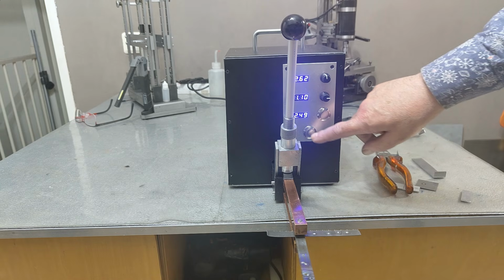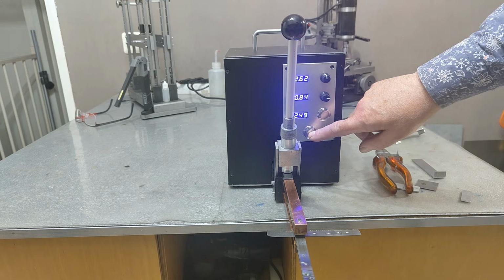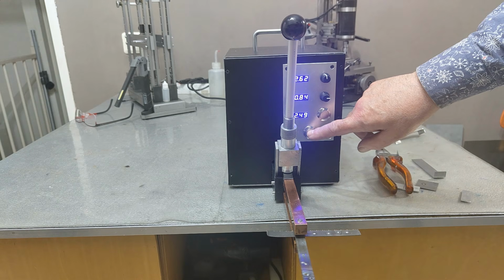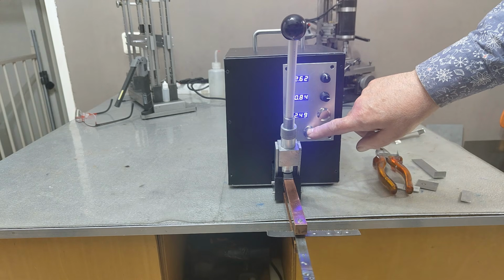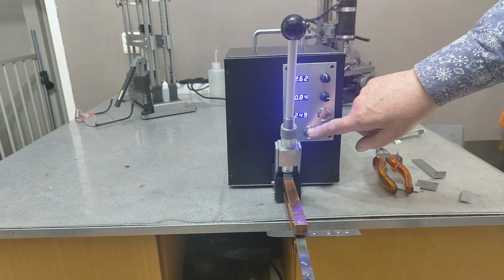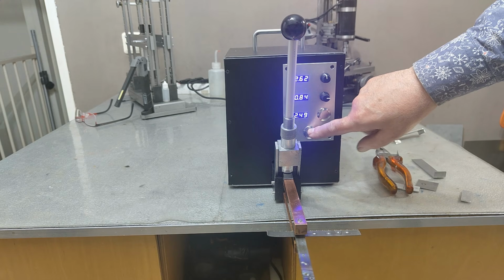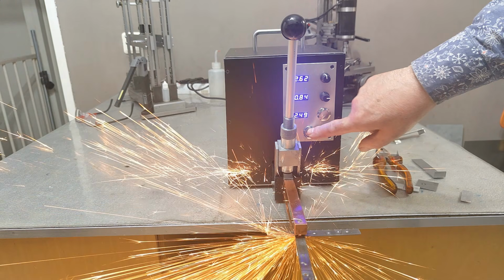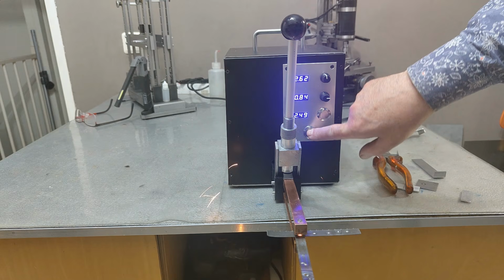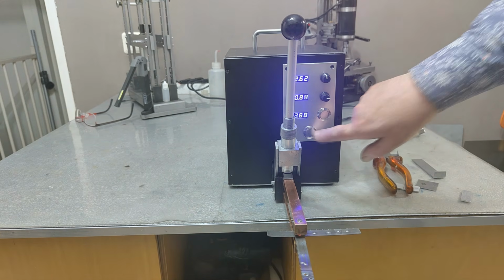Here, in slow motion, is what happens when you weld together two steel strips, each 0.7 mm thick, while the pressure applied by the electrodes is too low and the welding energy is too high. The molten steel is blown out from between the electrodes. It is a spectacular sight, but it is not what is supposed to happen.